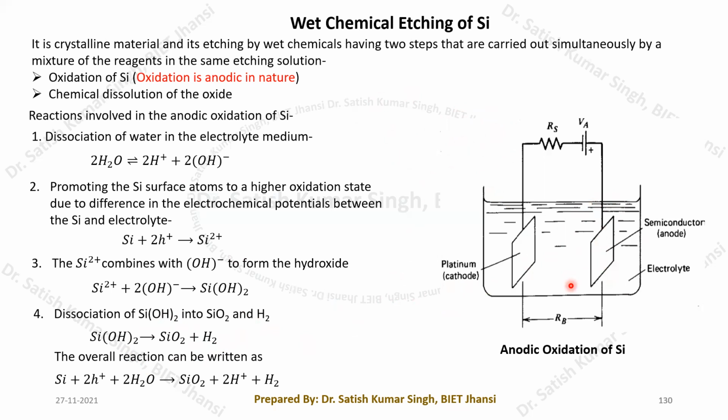Okay, so here we can see that a certain amount of silicon atoms will come out, and then a reaction takes place. In the case of thermally grown oxidation, the oxygen penetrates through and goes inside and then makes the reaction. So generally you will find that the thermally grown oxide layer has much better properties than anodic oxidation. So we generally don't prefer this one.